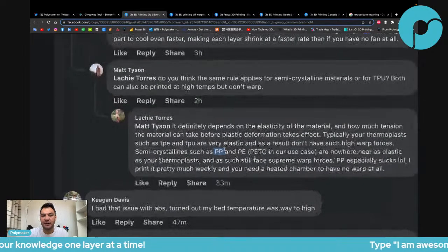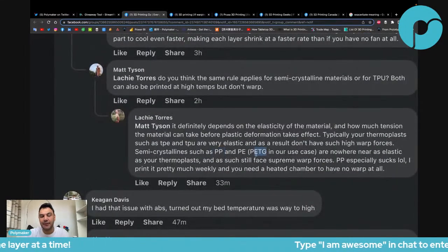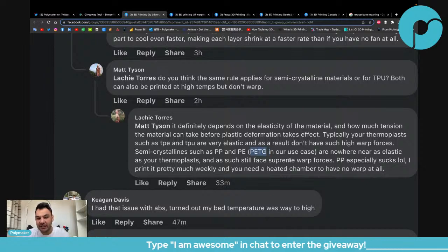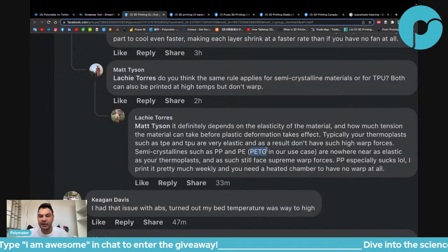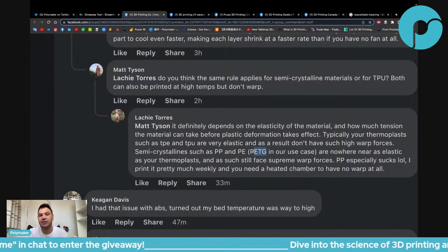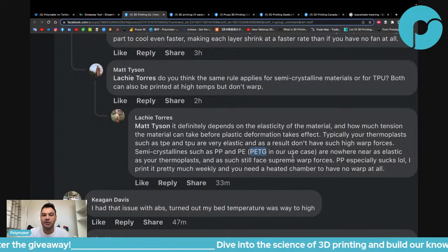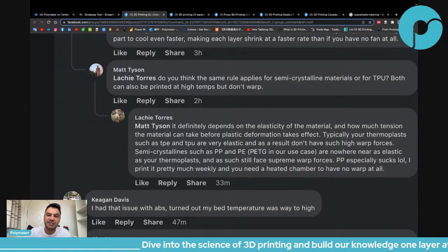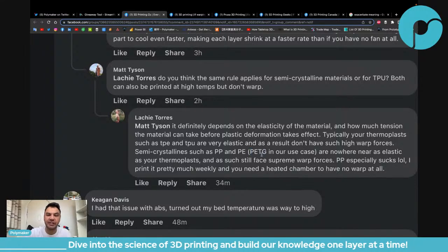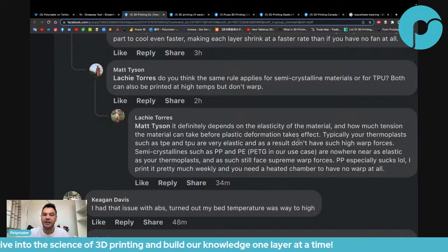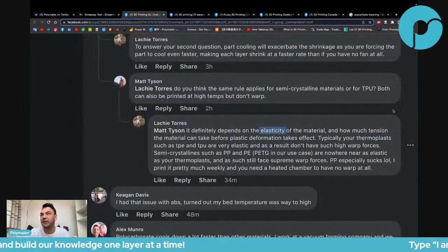That's different. PE and PETG are very different. For PETG, the fact that they use a different diol means it's very hard for PETG to crystallize. Actually, it doesn't crystallize, so it's not about crystallization. For me, it's about the elastic shrinkage, because the Tg of PETG is higher. I don't think it has to do with elasticity, or at least I cannot make sense of it.